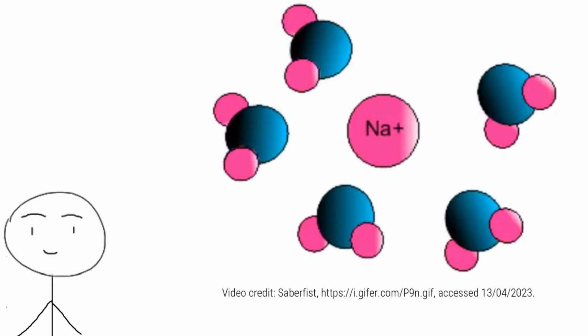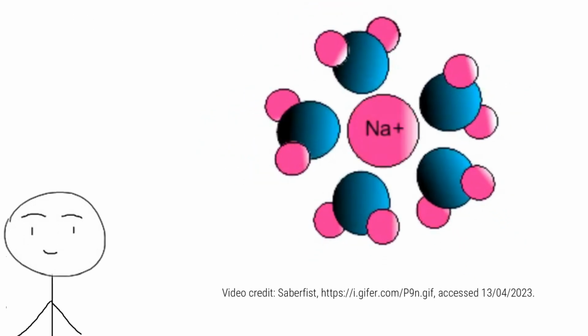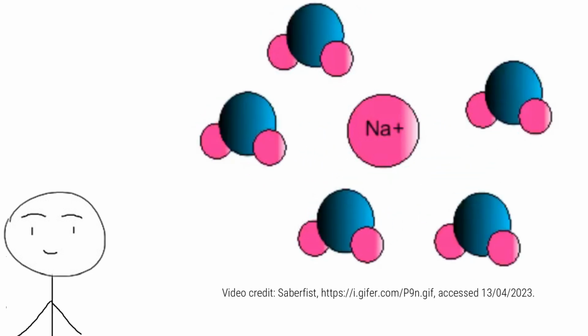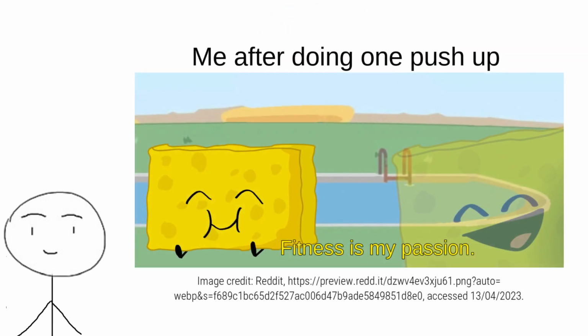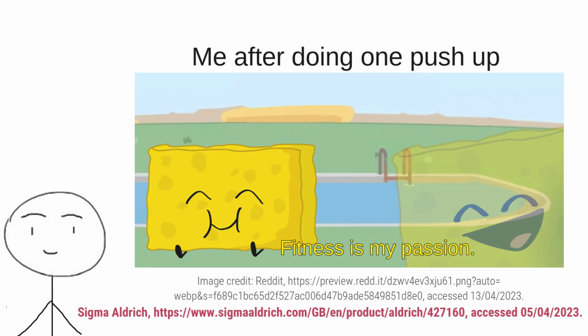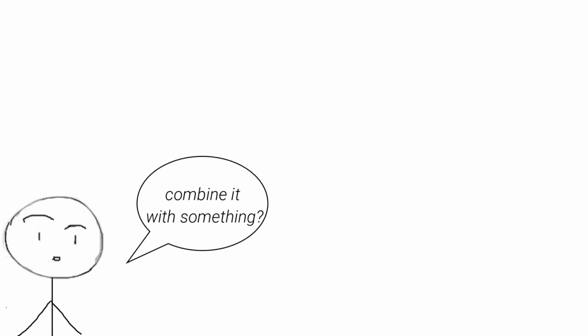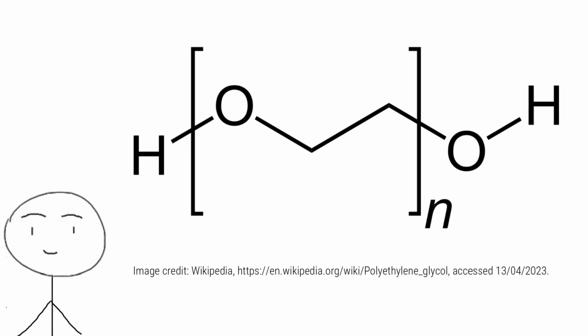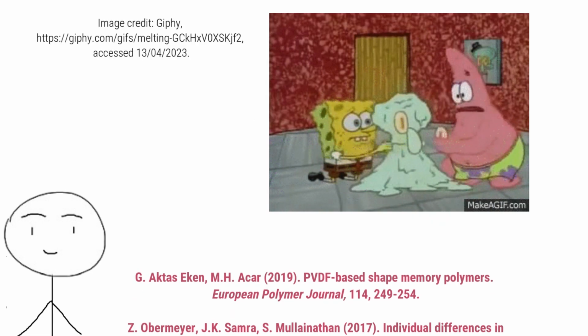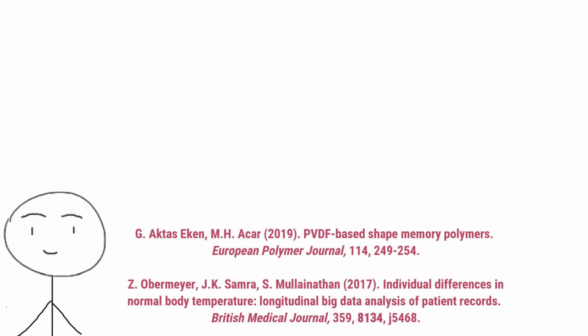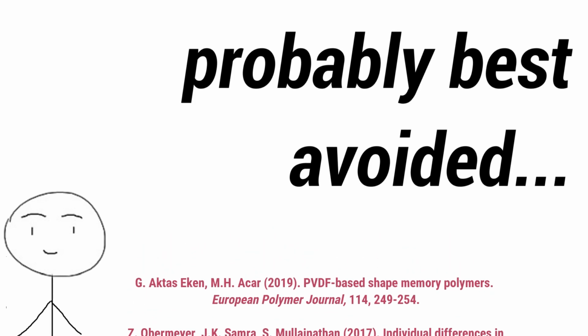Furthermore, when PVDF-HFP is paired with a mobile ionic salt, the glass transition temperature becomes dependent on ion-dipole interactions, and compared to hydrogen bonding, ion-dipole interactions aren't very strong. In fact, the TG for PVDF-HFP is minus 62 degrees C. Well, you could. Your best bet is adding polyethylene glycol, but that would give you a melting point range that includes your body temperature, so unless you'd like your phone screen melting in your hands, it's probably best avoided.